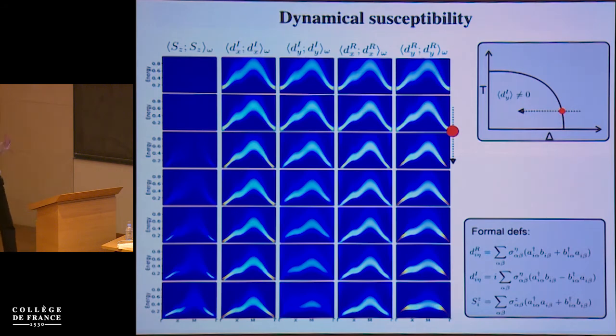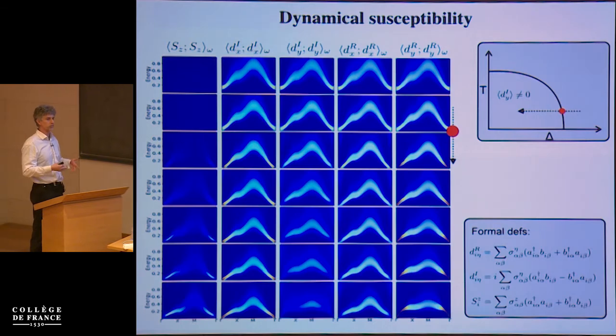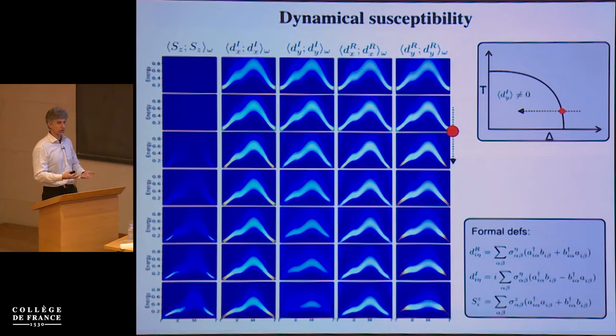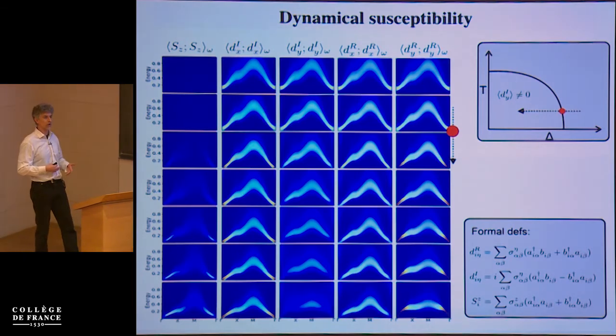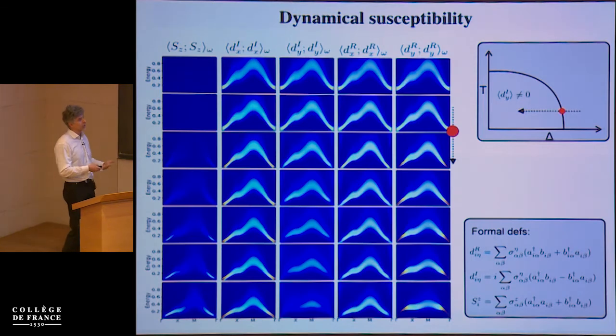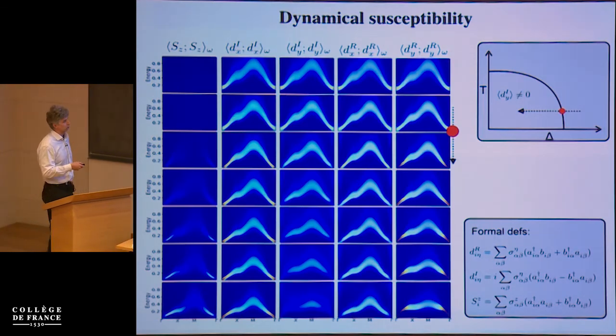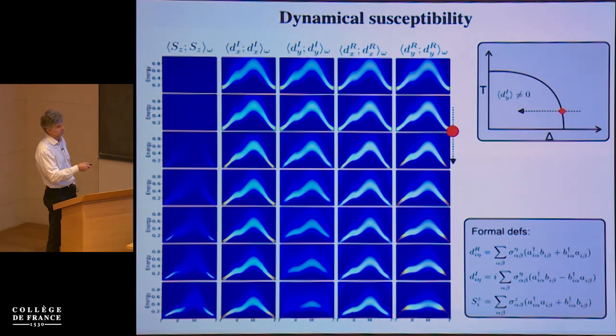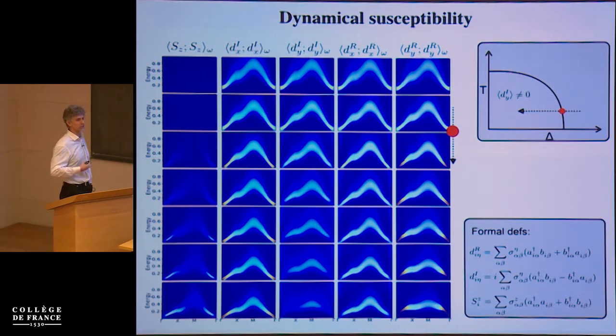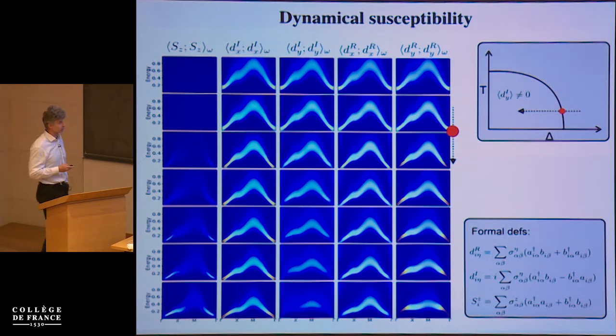The motivation for us to look at this was that we were interested in how DMFT performs. We did not know whether DMFT would reproduce these Goldstone modes, which are of course expected based on general symmetry considerations, and we also did not know how well our numerical implementation would describe it. I'll show you later that when we break this symmetry weakly, we indeed see the opening of a gap, so a rather small perturbation of the symmetry is reflected in this two-particle susceptibility.